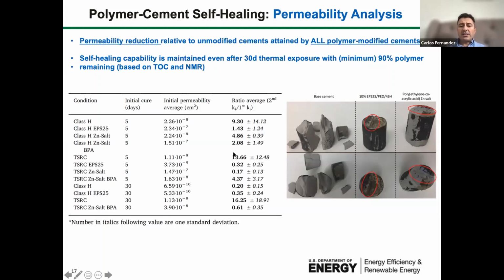Obviously, the reason for these different numbers is because we cannot control the width of the fracture. In these cases, we have been able to heal fractures up to 500 micrometers, so about 0.5 millimeter. 0.5 millimeter is a very large fracture in wellbore cement. First, you generate microfractures before you have this detrimental fracture event. But even with these large fractures, the polymer is still able to reduce the permeability of the cement in these formulations.